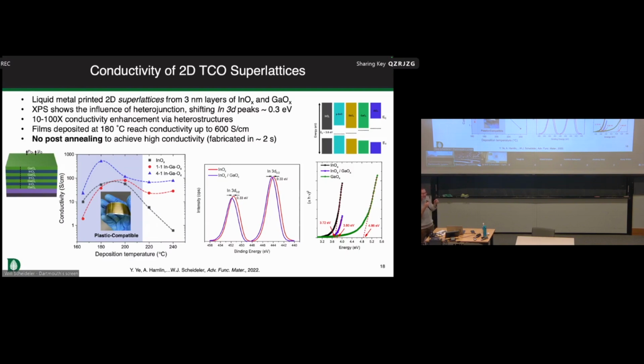And this effect is so significant because the layer itself is just a few nanometers thick. And you might think of that extent of that electrostatic effect as being approximately the Debye length. The indium oxide in this case is about as thin as its Debye length, at just a few nanometers.